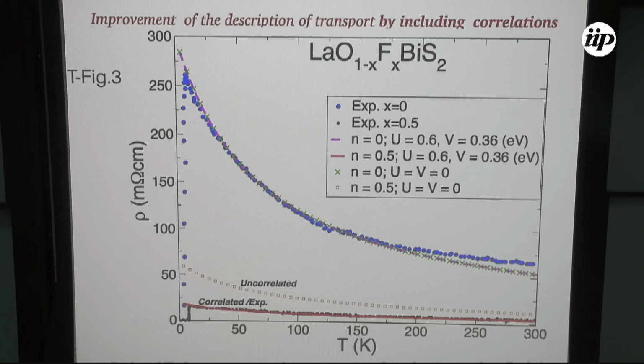Here I wanted to show how you improve the description by including the correlations, because there was a discussion about these materials. And here you see very quickly, down there, that if you use the uncorrelated resistivity result, it's quite far from the one when you have the correlations. So the fit to the experiment is very good.